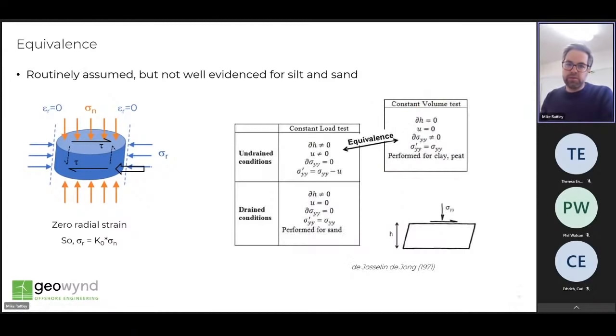Since drainage can't be controlled in the conventional apparatus, an assumption of equivalence is required to simulate undrained conditions, and that uses a constant volume condition. That is essentially where the normal displacement of the specimen is prevented during shear, and the resulting changes in normal stresses are taken to be representative of variations in pore water pressure occurring, or that would have occurred, in a truly undrained test. This assumption is quite well demonstrated for clay soils, but not well evidenced, to my knowledge at least, for silt and sand, so some degree of caution is required there.